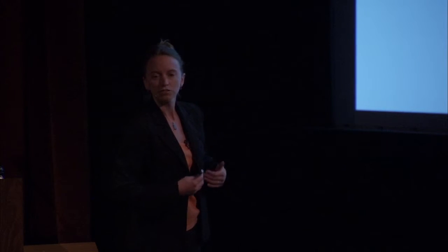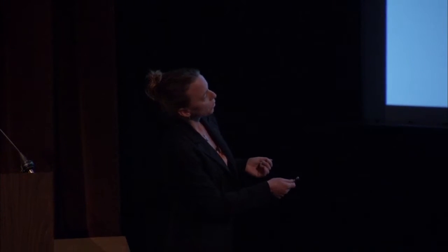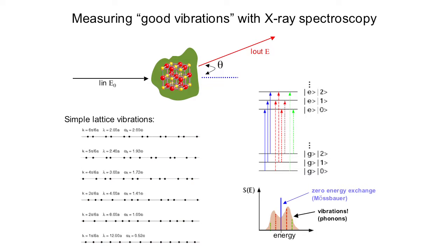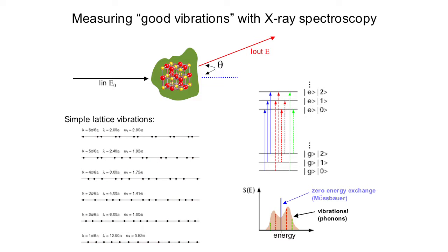So the low energy excitations, which are long wavelength, also called long wavelength, are the acoustic modes in our sample. And the higher frequency ones contribute to other pieces of information, such as thermal conductivity or the thermal pressure of the material. And so if we take our measurement, which we can see in a schematic here, we scan around this energy, and we are then able to probe all of these different vibrational states.